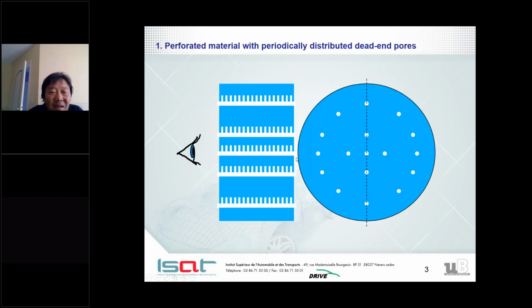So the pancake absorber, how did we come to this idea? Well, we had some experience in the study of porous materials, and we noticed that perforated materials, which are a particular porous material, bearing lateral quarter wavelength cavities like this, distributed periodically along the main perforation, were giving very interesting results on the low frequency sound absorption. So we set out to study theoretically and experimentally if this kind of structure was possible.